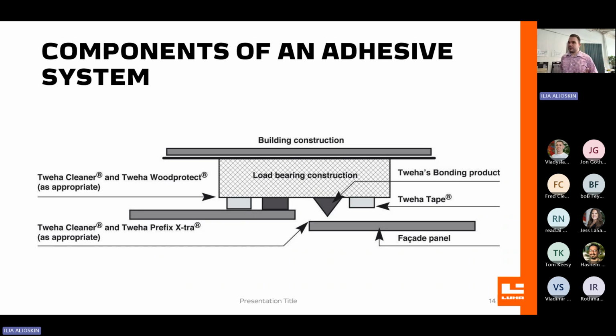And then we have Tweha Tape, which is a double-sided stick tape. And then we have the adhesive. So the tape acts as an instant adhesive while the bonding product actually sets in place. So when we start installation, we want to start on the bottom row, and we put a dead load, like a 2x4 or a metal angle, to keep the first panel in place so we can stack. But essentially, when you stick the panel on, this double-sided tape keeps it in place, and the adhesive will grab in 24 hours. It's not fully cured, but it will be strong enough so you can stack. And in 5 days it's fully cured, and then the tape is just there for that initial method. We don't rely on the structural performance of the tape for the life of the cladding.